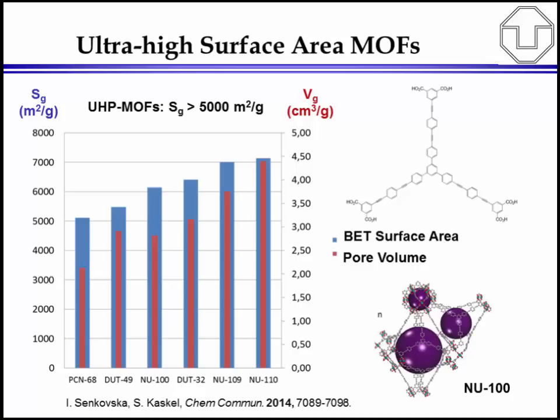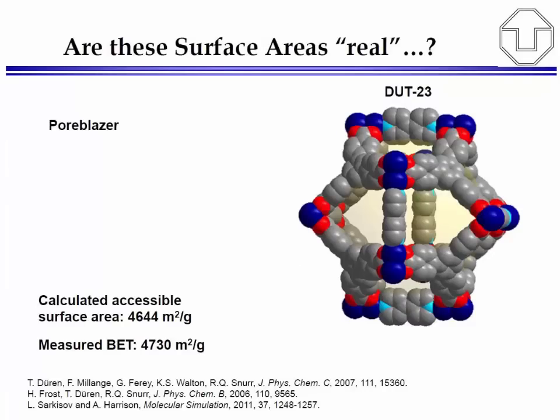But you see also that there are some very complicated ligands and linkers involved, but you can achieve extremely high specific pore volumes. And we call these materials now ultra-high specific surface area MOFs, or ultra-high porosity MOFs, because the surface area is higher than 5,000 square meters per gram. Now, I'm often asked, is this a real surface area, or is this just fake or an error in measurement? And on the next slide, I will try to address this problem a little bit.